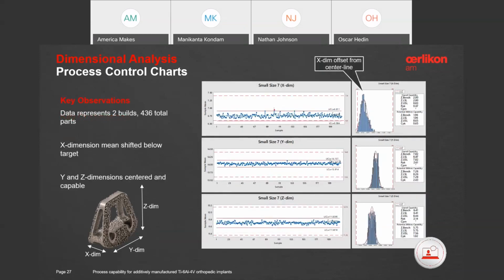Some cases, however, exhibit lower process capabilities. Notice how the top chart shows an offset from being mean-centered. But the measurements are still very repeatable. As long as the process remains consistent, we can solve the center shifting by simply rescaling the affected models. And this is important because it illustrates a recurring problem in our AM production, the need for part-specific scaling factors.